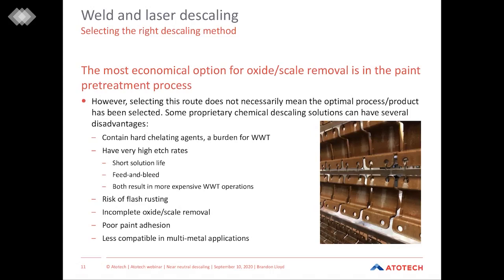Some of these have very high etch rates, and what this results in is a very short solution life. Some applicators will implement a feed and bleed type system where they send off some of the solution and replenish with new. But again, this results in more chemistry being sent to wastewater treatment. And both of these result in a much more expensive wastewater treatment operation. There are risks of flash rusting, as you can see exhibited in the image on the right side of this page. Some offer incomplete oxide or scale removal. We still see poor paint adhesion with some of these, and they can be less compatible in multi-metal applications as well.